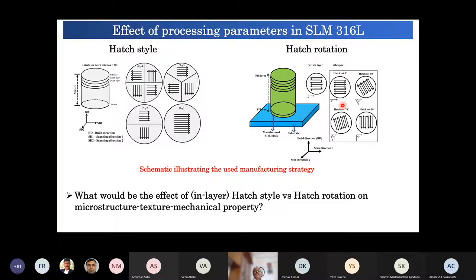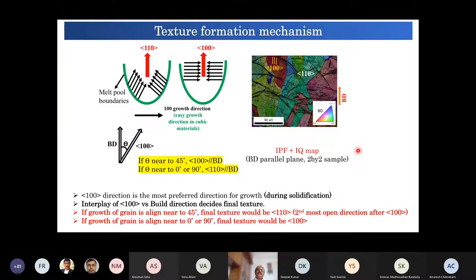We also tried to change the hatch style of deposition, and we applied different sizes of hatch style and hatch rotation. So style means these directions are totally different in four quarters of the build. And in this case, we have just alternated the directions, and the entire system was rotated this way.